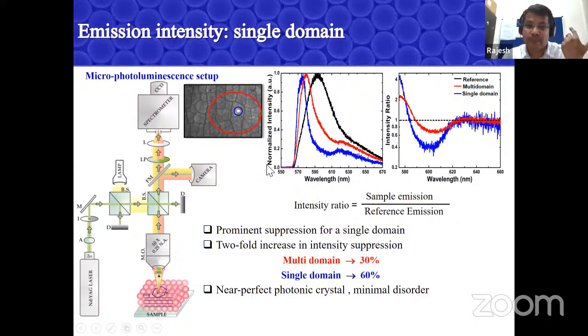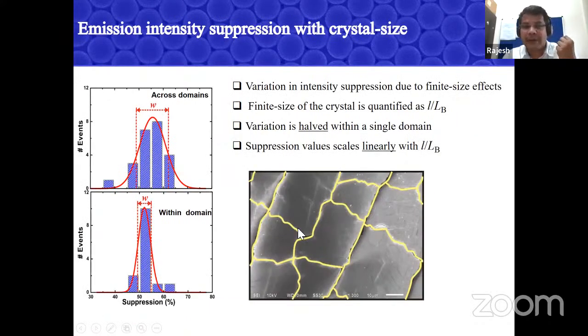The answer is no. Okay. So you take this kind of sample, you measure hundreds of domains, and you look at the histogram. There are domains which give you emission suppression close to 70%, but there are domains which give you less than 30% or so. So it actually varies in the samples. And that happens in any nanophotonic structure because there will be a lot of variation in the thickness of the samples. So you need to have a very precise measurement of where exactly you do measurements.